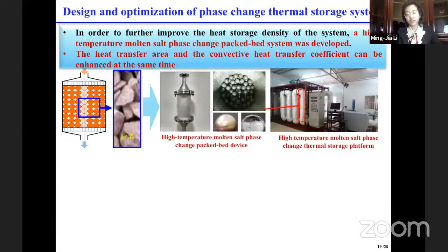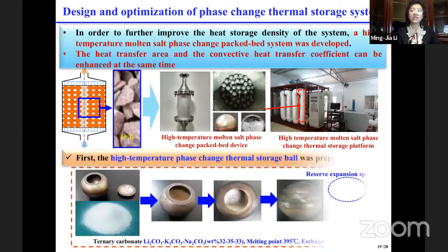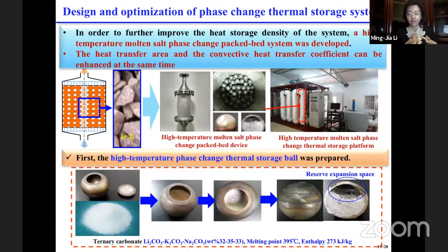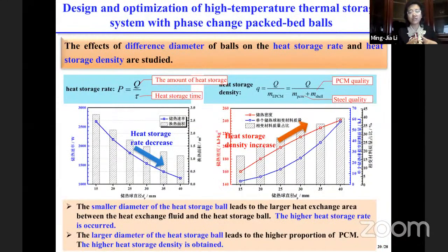And what about the phase change material? For the phase change material, definitely we need a phase change ball which can contain this kind of material. Another advantage of adopting this ball is that we can enhance the heat transfer area, and the convective heat transfer coefficient can be highly increased. After different parameter analyses, I just choose a very simple example here: different diameters always give different performance results. From these 2 diagrams, you can find out that the smaller diameter of the balls leads to a higher storage rate. But from the right-hand side, you will see the larger diameter of the balls leads to a higher density.